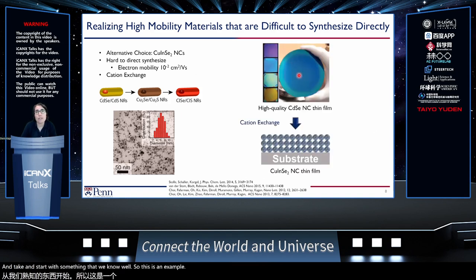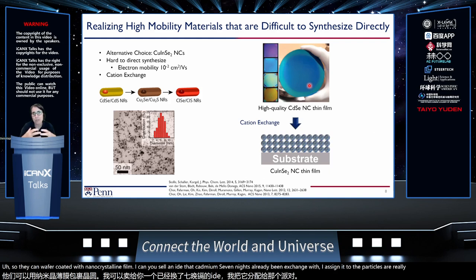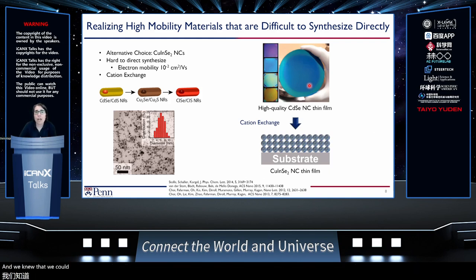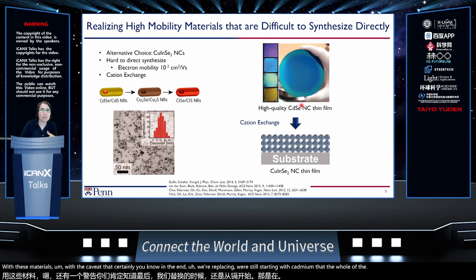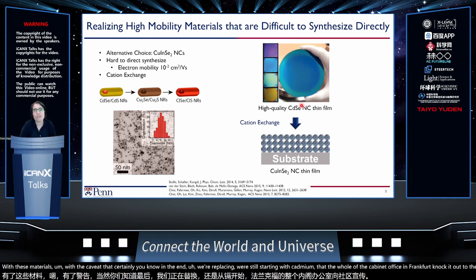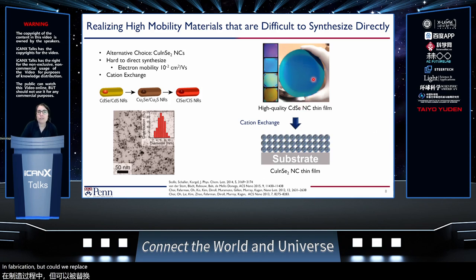So this is an example, again, that I showed you before, of the 4-inch diameter silicon wafer coated with nanocrystalline cadmium selenide. That cadmium selenide has already been exchanged with thiocyanate, so that particles are really close together. And we knew that we could make high mobility transistors from this. And the question is, could we start with these materials, with the caveat that in the end we're still starting with cadmium, although in principle the cadmium wouldn't be a concern to the community because it would be used only in fabrication? But could we replace these materials and show that we have this versatility to exchange materials in the solid state and also form copper indium diselenide?